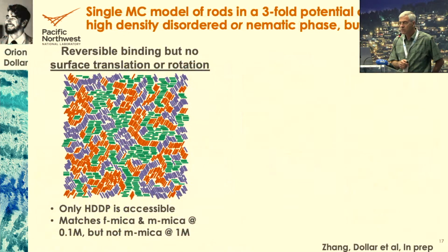Why? If we look at Monte Carlo simulations, these were done by Orion Dollar, who's a student of Jim Pfaendtner, our collaborator at University of Washington, and working with Chris Mundy, my collaborator at PNNL. What you will find is that if you have reversible binding to a surface, but you don't allow translation or rotation, you can never leave the high density disordered phase. You will always see this phase at high protein coverage in a threefold potential, because there's all three directions. And you can see why, because a little domain nucleating over here doesn't know about this one over here, and so they form independently and they all get stuck. It's a kinetic trap. It's not the equilibrium state.